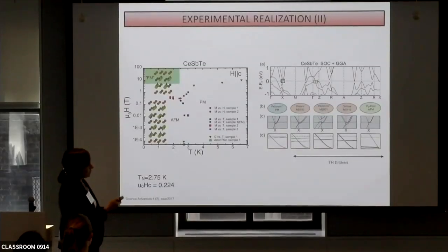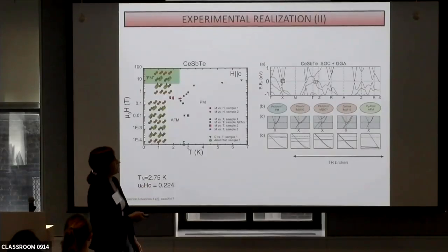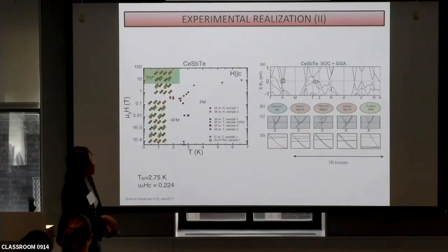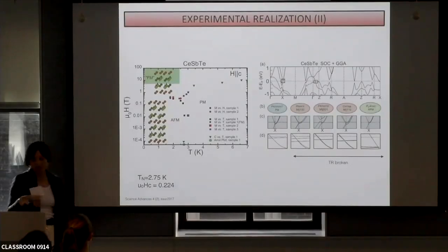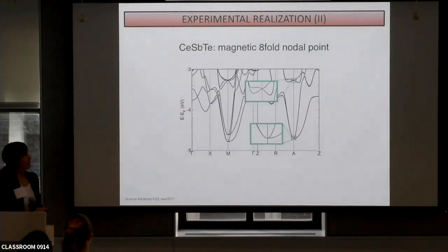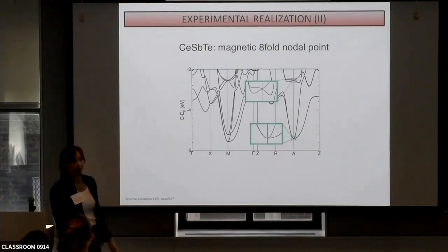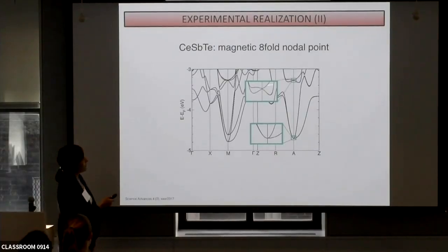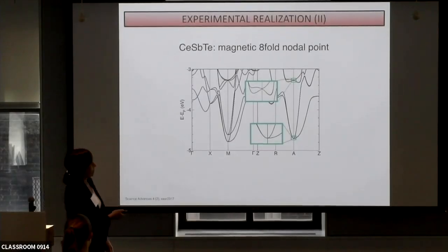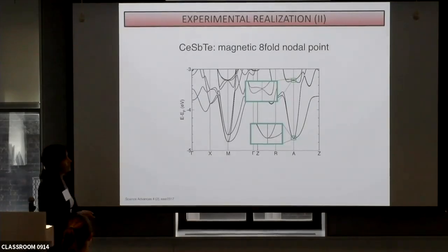In the 001, it also splits. Then we have these crossings, and for the antiferromagnetic phase, we recover the flat line because time reversal symmetry is combined with translation, and it's preserved in this way. And if we go way below the Fermi level, almost minus 5 eV, the eightfold magnetic crossing can actually be realized at the R point.